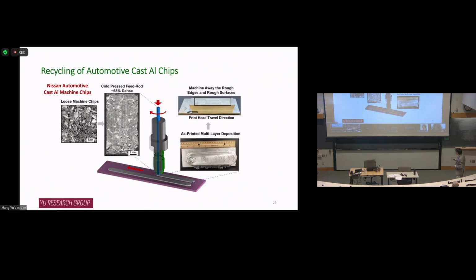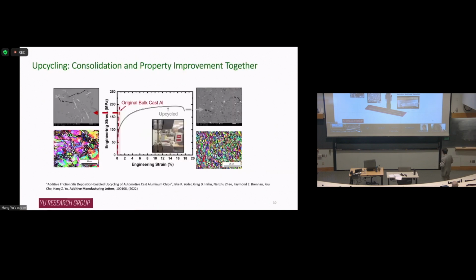And it turns out we can get a fully dense material, even though the feedstock is not fully dense. This is because we have sufficient material flow, compression, and shear, so there's some in-situ consolidation process. Of course, there are some rough edges, so we can remove those and we get a block. We can fabricate a tensile bar and test the mechanical properties. This is as-printed material, no heat treatment. This is what we get.